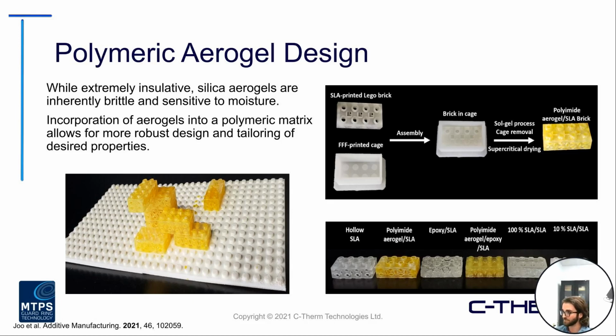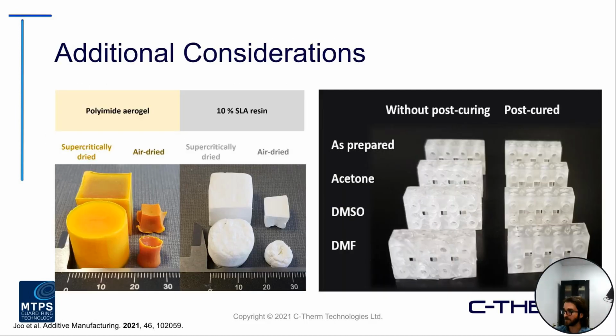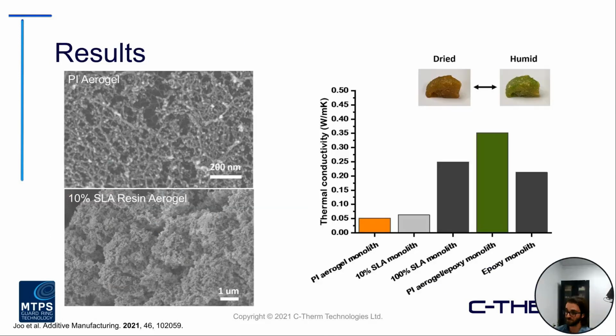So you can see the overall process that was used here in the SLA printing technology. They had various different materials, so polyimide, aerogel, SLA, and epoxy, with varying concentrations across the board, as you can see on the bottom. A very well done paper, I will say. If you have a chance to go through this, they had a lot of different studies and aspects of the material done. They looked at the drying process and post-curing with different solvents. Obviously, a lot of considerations were taken into account here, but at the end of the day, looking at those final thermal conductivity results, and again some supporting SEM imaging on the left, they were able to see that in all cases, fairly low thermal conductivities were obtained.